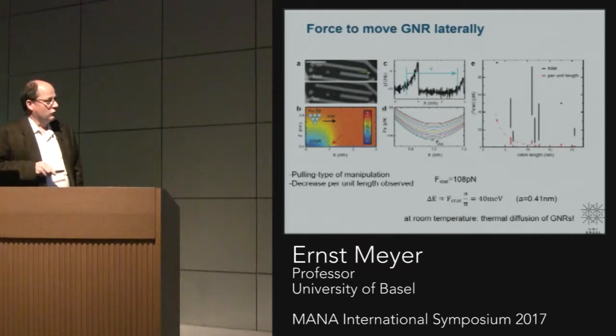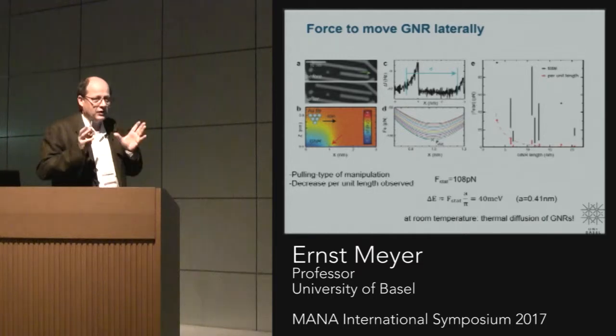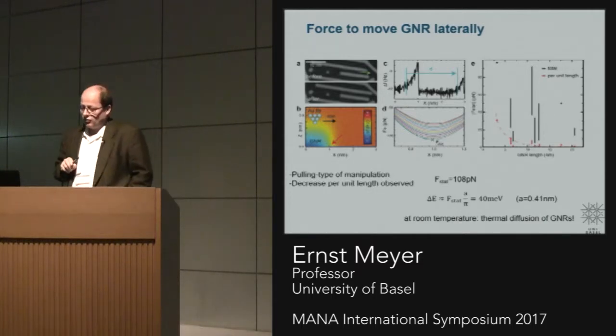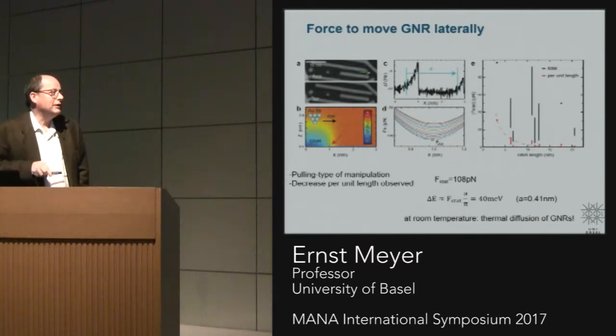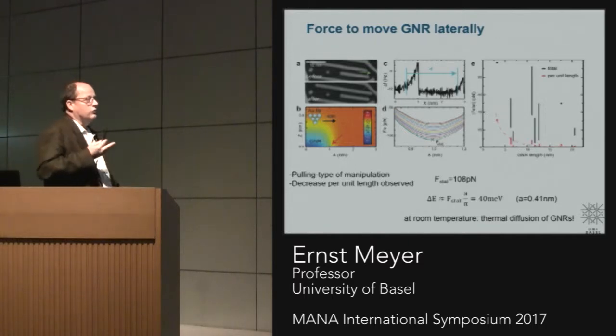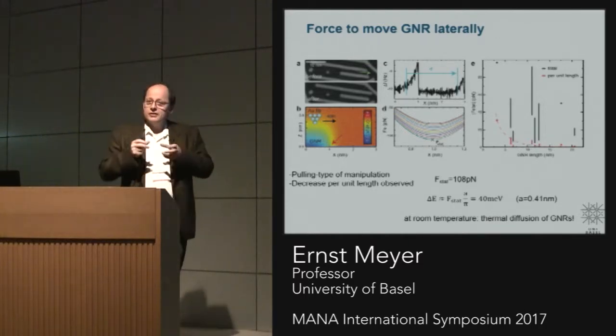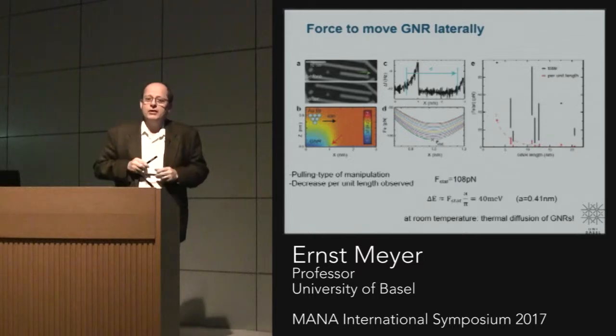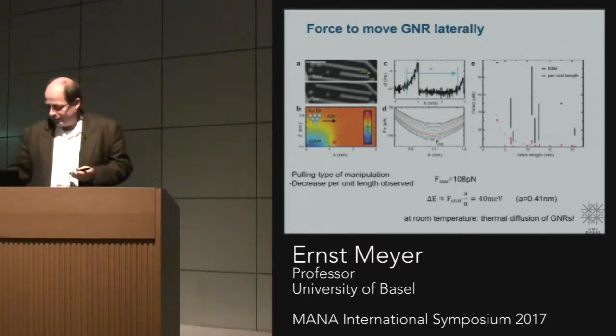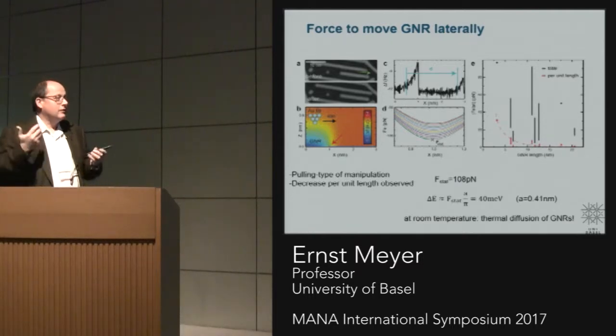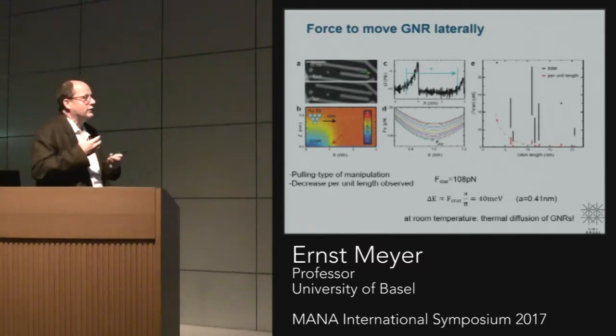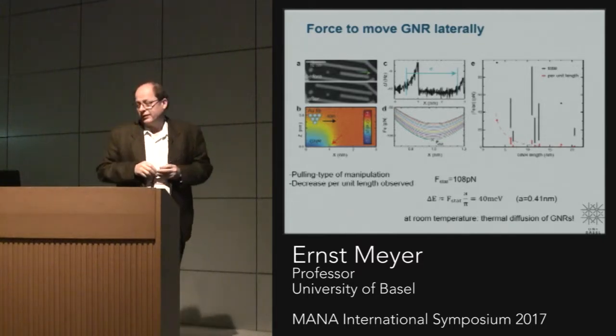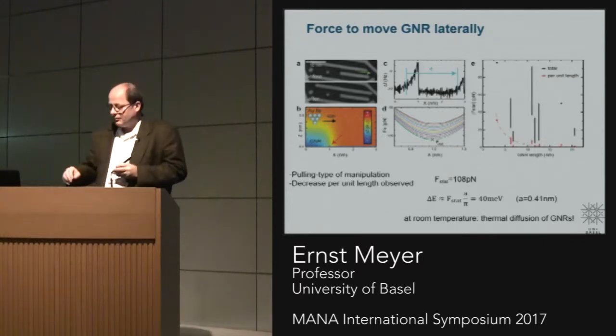And so also if you take this, let's say 100 piconewton, you can estimate about the barriers which have to be overcome. So this is around 40 millielectron volt. So if you would do the same thing at room temperature, these ribbons would already diffuse around. So they are really relatively easy to move around, and that's also the reason why we call that already a sort of a superlubricity regime.